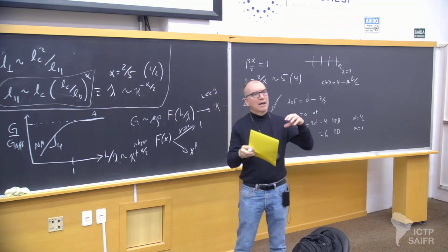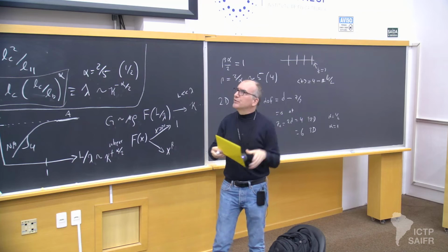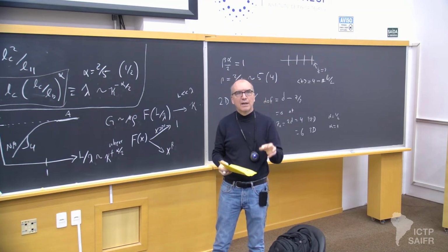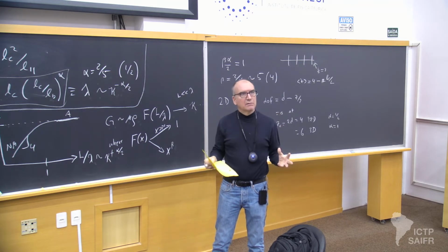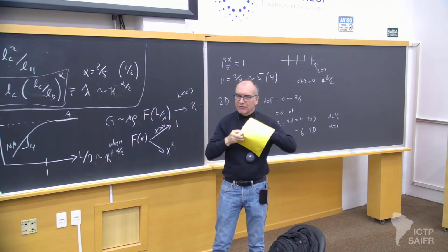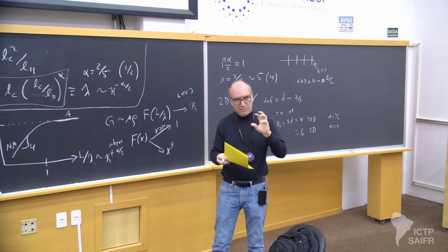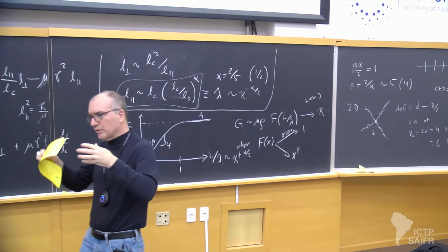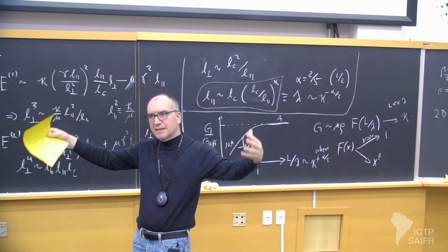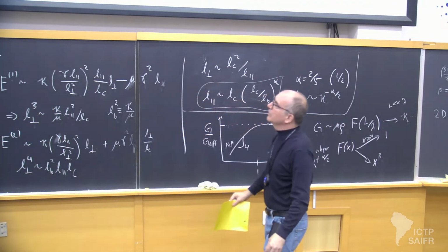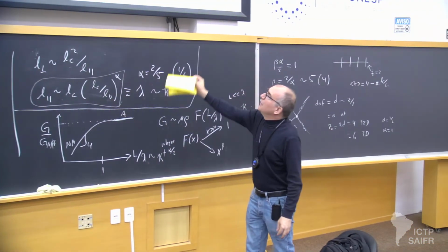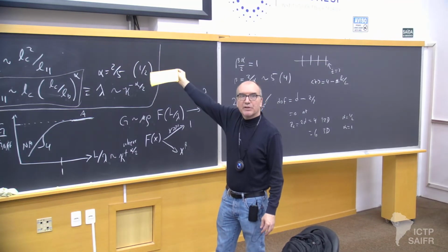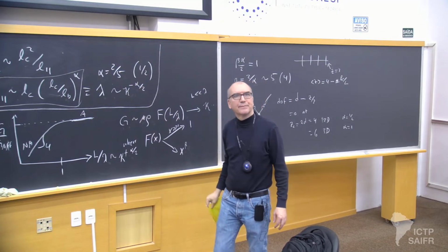Once we dilute that FCC structure, you get a random network that has no unit cell, and even though it has a local structure, which is admittedly anisotropic, there's no local cell. You can scale it up to arbitrary size and get distinct random structures. The unit cell doesn't quite permit that, and so they were not able to go to as high molecular weight, but the results are still basically consistent over the range they can get.